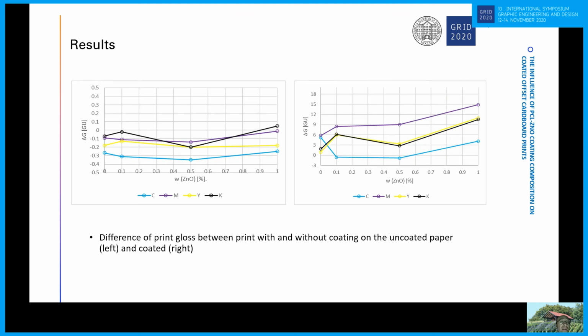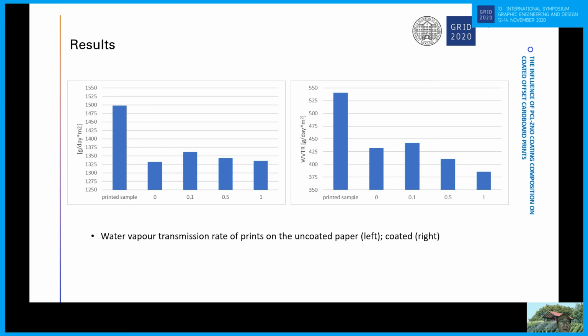The print gloss, we can see that the changes on the uncoated paper on the left is almost none, and on the right we can see that adding zinc oxide is really increasing gloss. Water vapor transmission rate, we can see on both that coating improved barrier properties of the investigated papers. On the uncoated paper, where probably part of the coating is absorbed, the PCL is giving very high result, while adding zinc oxide nanoparticles is not improving, which is not the same on the coated paper, where we can see that the lowest water vapor transmission rate is achieved with the highest investigated zinc oxide concentration.